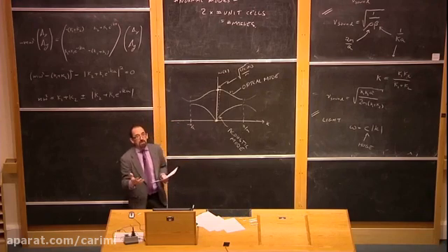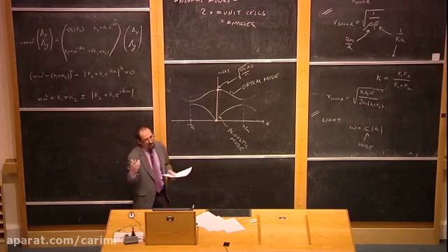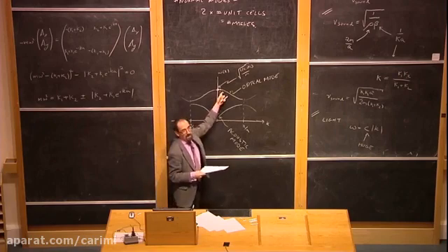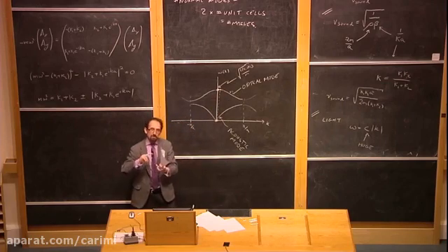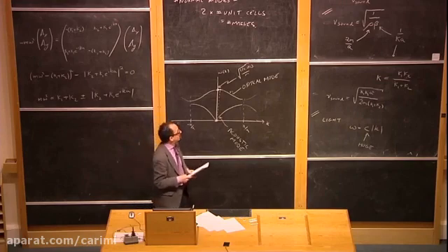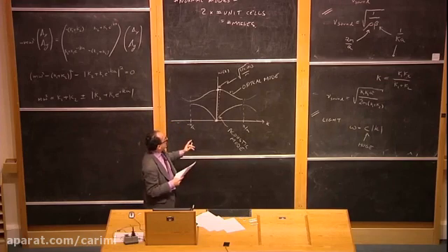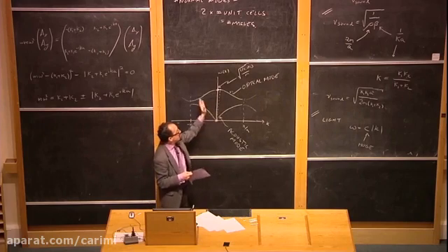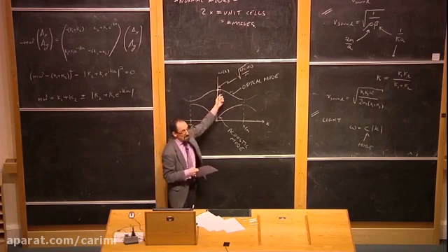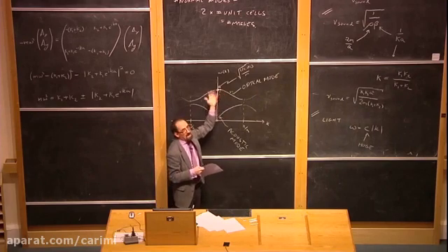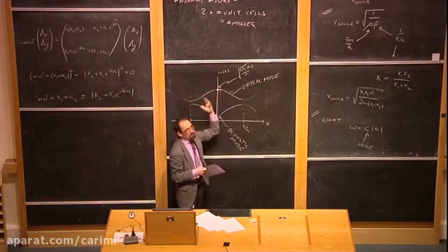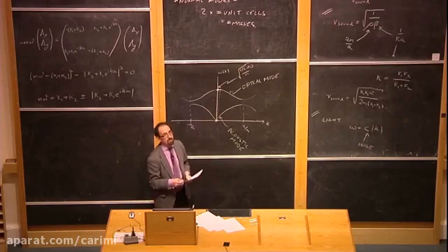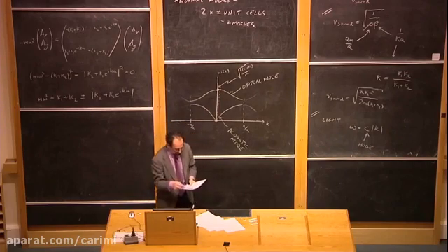However, there are more complicated processes that can occur involving photons and phonons. For example, absorb 2 photons and emit some phonons. That's OK because the angular momentum of the 2 photons can cancel, and you can still have conservation. And it's still the same principle that it's very hard to conserve both energy and momentum in any sort of interaction between phonons and photons unless you're getting optical modes into the game, because you need to get high frequencies into the game somehow with phonons. And the only way to get high frequencies with small wave vectors in phonons is to use the optical mode. OK? So that's where the name comes from.